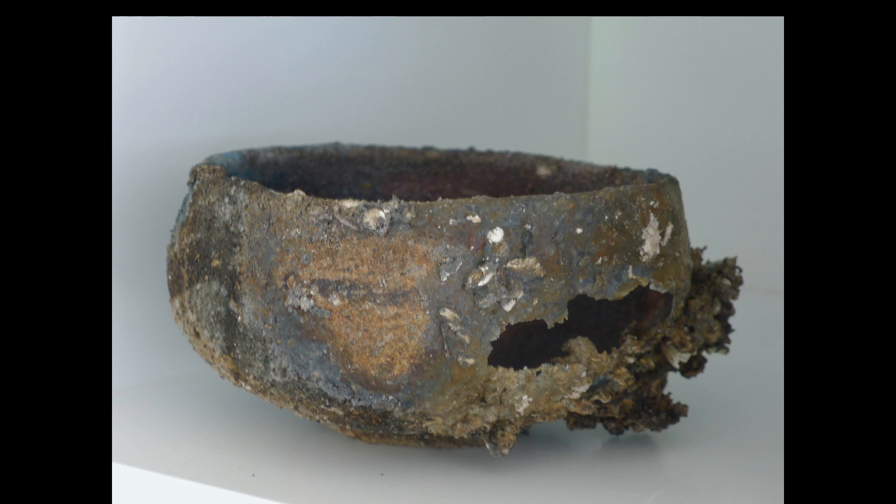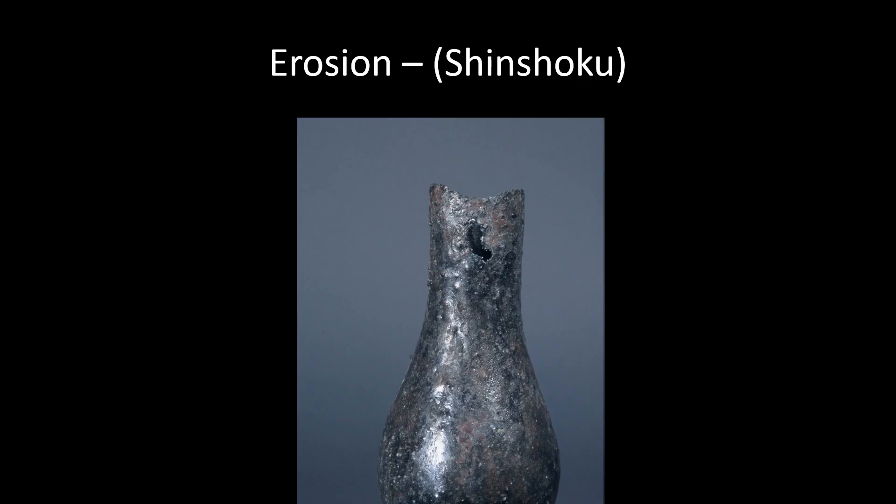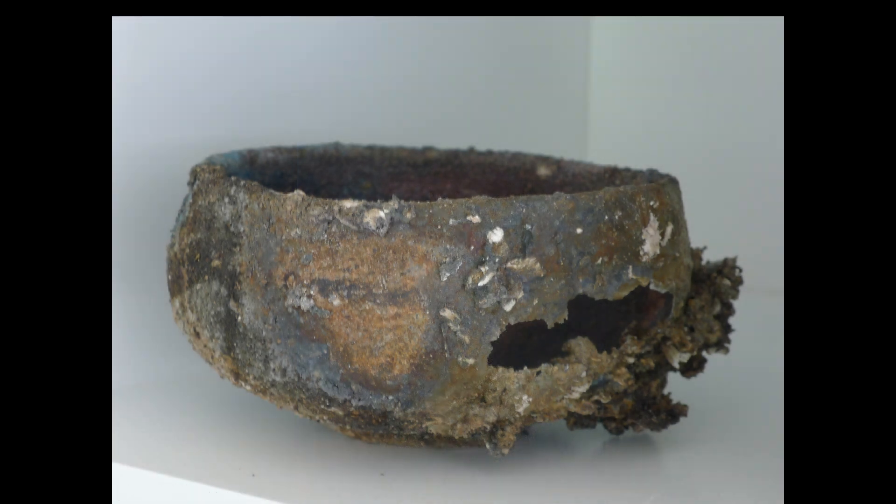Here's a piece that started out as an even neck and lip. After the firing, you can see that it actually ate a hole through the piece, and if you were to touch the edge of that, it's razor sharp. What's actually happening is there's so much ash hitting these pieces at such high temperature that it melts the clay and drips down the piece, and it keeps doing that until it eats the piece away — sometimes completely like this.